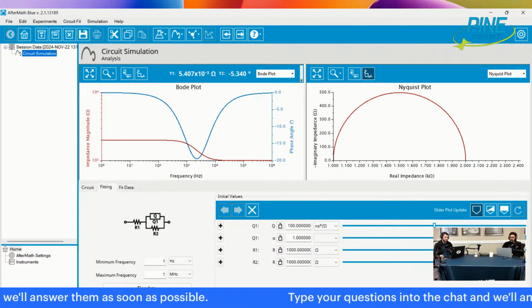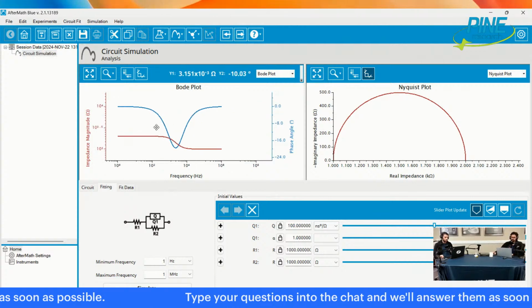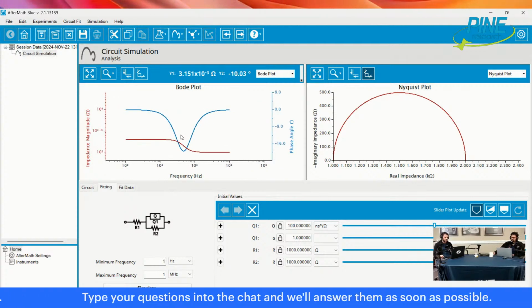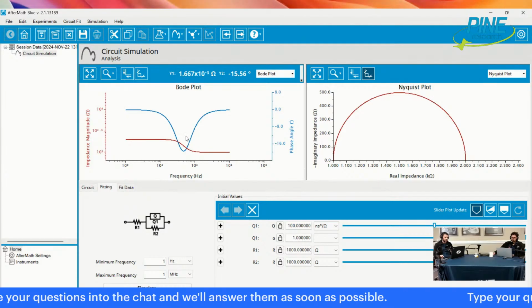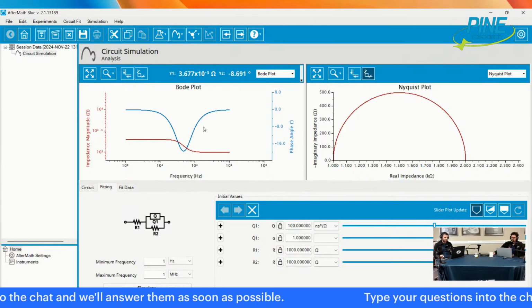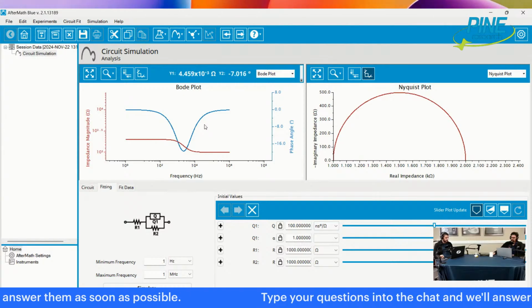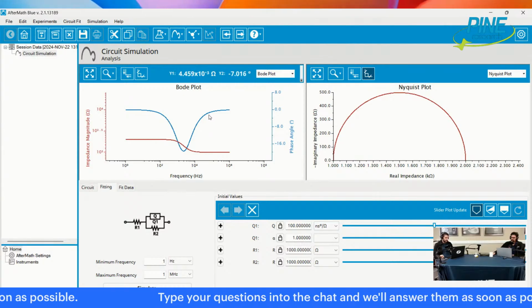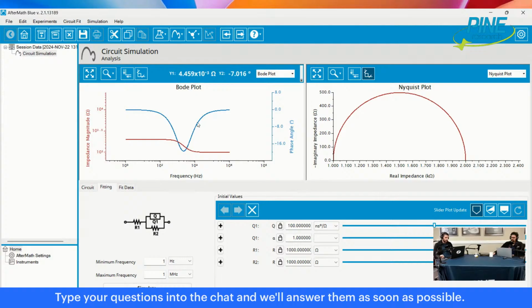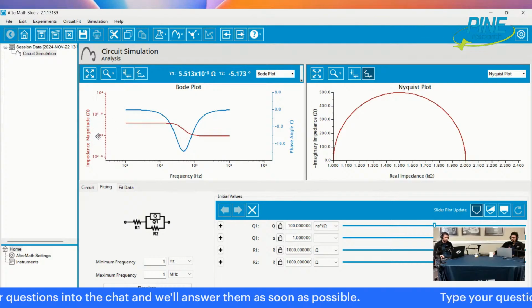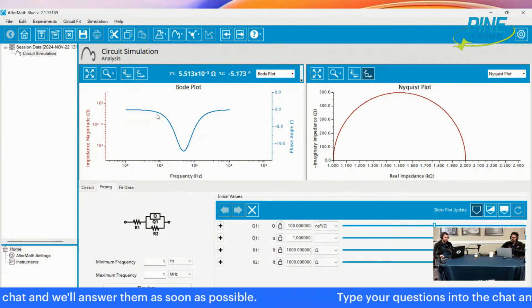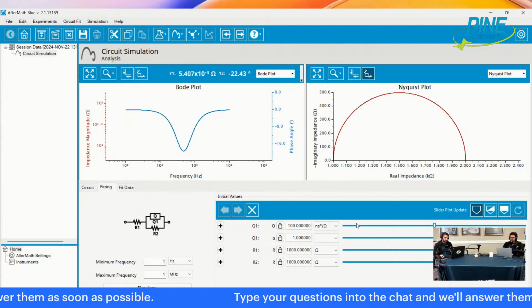So what I'm gonna do is I'm gonna change some values and I'll show you what one explanation for that could be. So this is a peak right here. You're observing this kind of peak, which is some interface. You don't typically always get a peak in the phase angle plot, for example. I'll just get rid of the other one. So this is the phase angle. Just sort of isolate this to get to the point of your question.